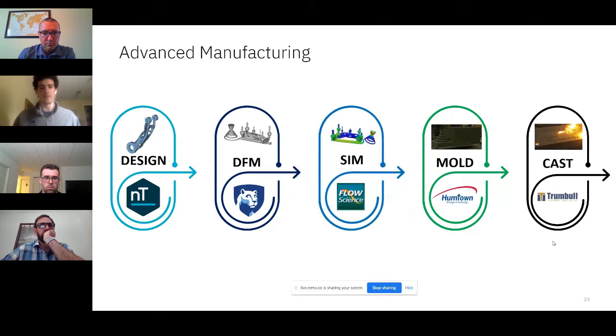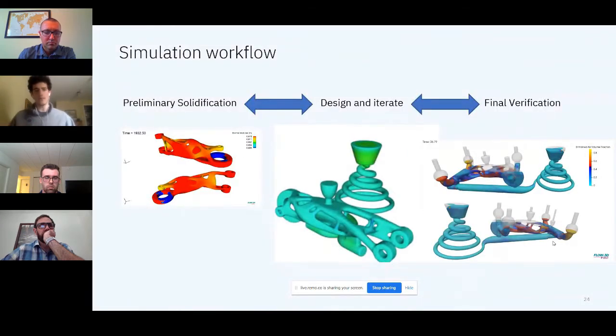Next slide, please. So now I'm going to talk more about the simulation. So basically, the way we started with our workflow for the simulation with working with Flow 3D is we started out with a solidification model and figured out where the hot spots were and where we would need to place risers. Then next, we tried this design where we were trying to minimize the amount of area we needed for this mold. So we put a conical helix sprue right next to the casting and then just put one riser on top to see what would happen. And when we did this, we were still getting areas where we didn't fully fill the casting, and also we would get hot spots during solidification.